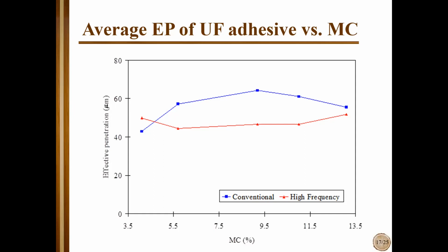But with higher moisture content, it starts to decrease because wood is not so dry anymore, it's more moist. So this attraction force is not present anymore, but moisture which we have in the adhesive bond allows adhesive to move, to penetrate.